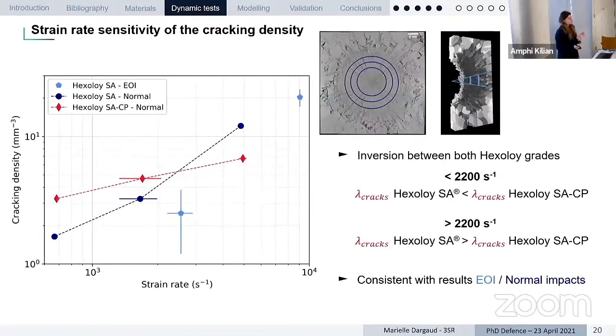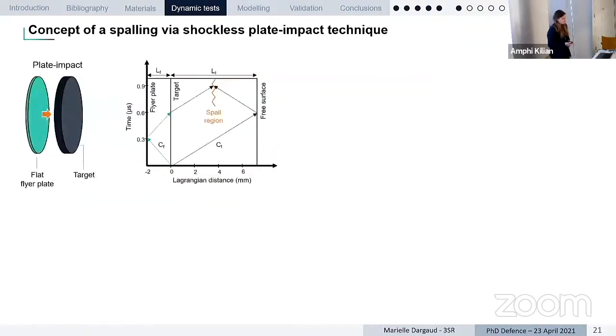Now we also want to be able to quantify the strength of the material under tensile loading. To do this, we need an experimental configuration which can generate a controlled tensile loading in the ceramic. So for this, to have access to a high strain rate, we use a plate impact configuration.